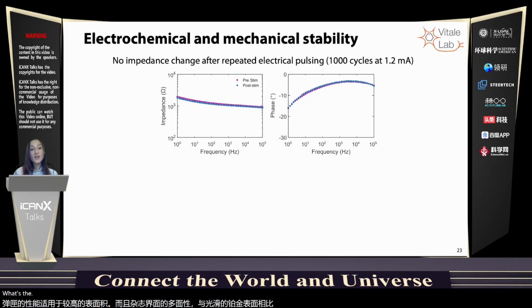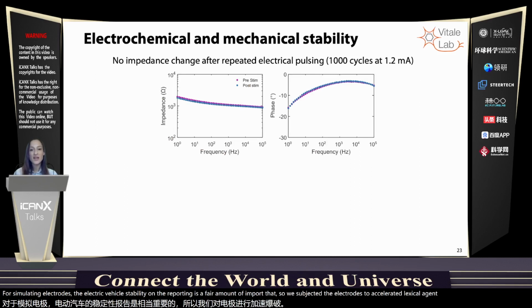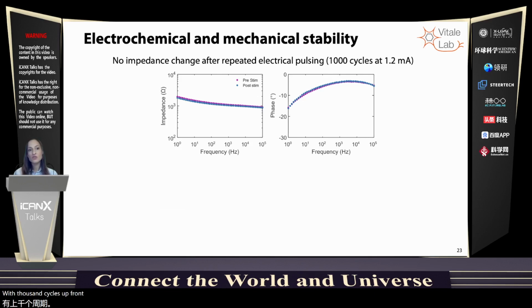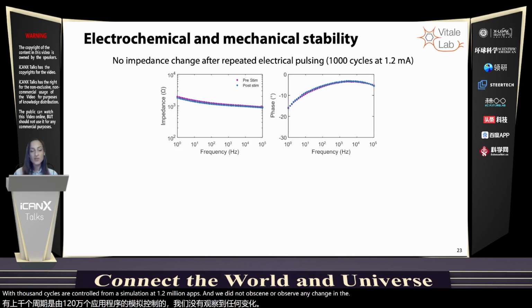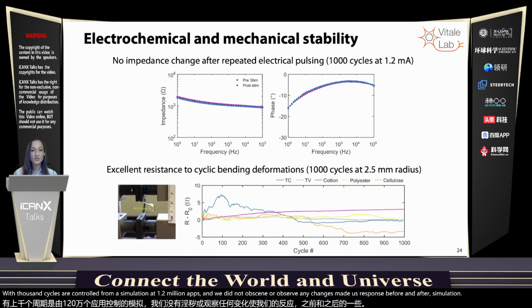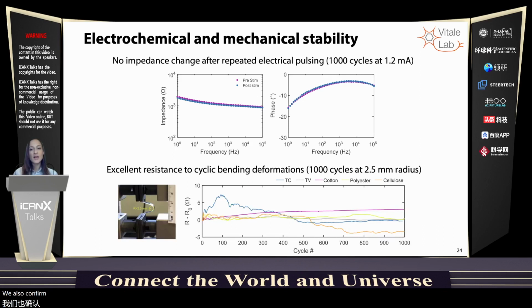For stimulating electrodes, the electrochemical stability under repeated pulsing is of paramount importance. So we subjected the electrodes to accelerated electrical aging tests with 1,000 cycles of controlled current stimulation at 1.2 milliamps. And we did not observe any change in impedance response before and after stimulation. We also confirmed the excellent mechanical stability of MAXtrodes under repeated bending.